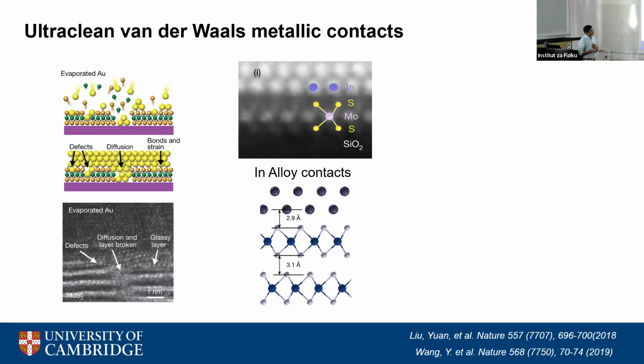What they did was they performed electron energy loss spectroscopy on the sulfur. They took many layers of MoS2, did electron energy loss spectroscopy at the sulfur atom, and looked at the interaction of the sulfur atom with its neighboring sulfur, which was a van der Waals interaction, as you would expect in pristine MoS2.